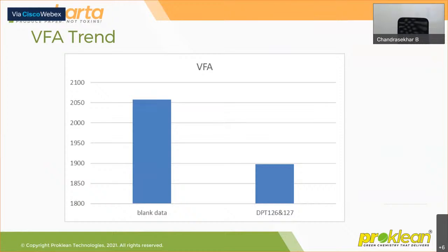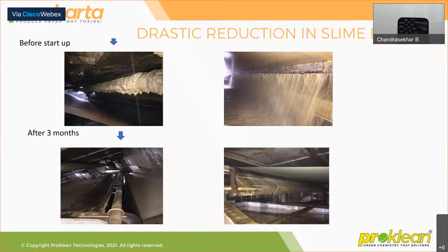All the mills that are using our products have shown a reasonable and significant reduction in VFA, which is a very important factor as far as the paper odor is concerned. 15, 20, 30%. There were some mills which had huge accumulation of slime, as you see on the top. After ProSol Plus was used, the 126 and 127 combination, within 3 months the slime got dissolved, and this was a clear operation in the mill.